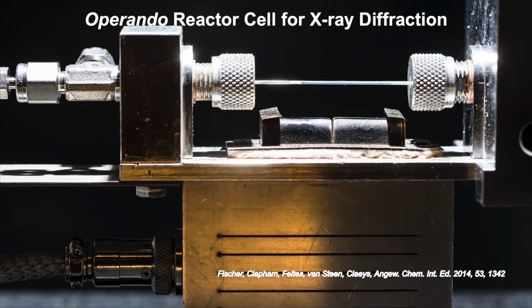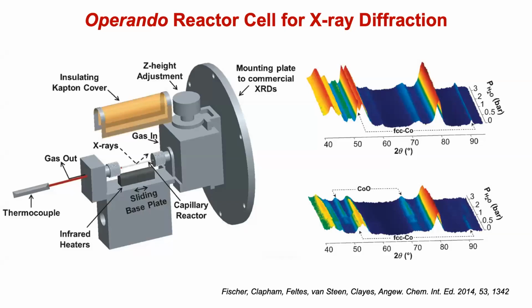These people have been using it for X-ray diffraction. Actually, it's also a commercial system to my best knowledge. Here you see it on the left. You can find more details in this paper, where you have this insulating Kapton cover, X-rays in, X-rays out. And the most important is that also the thermocouple is rather positioned well, at least close to the bed. And so people have been using it, for example, because the group of Claeys is working a lot on Fischer-Tropsch, and it means that he follows, for example, cobalt systems.